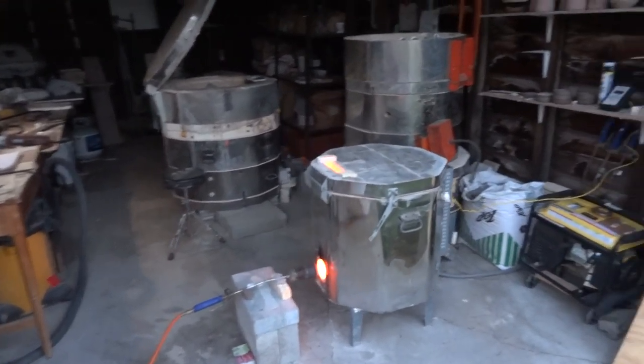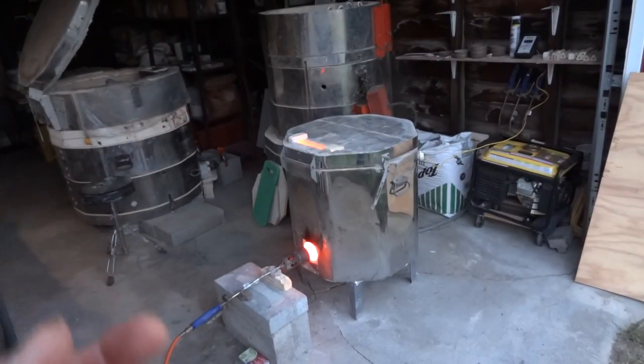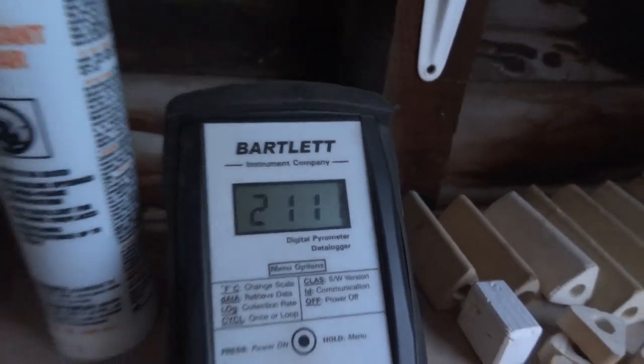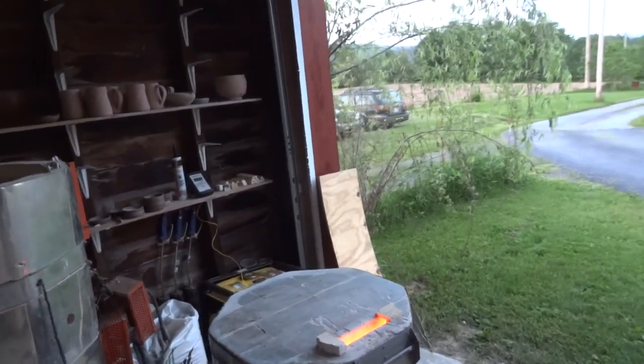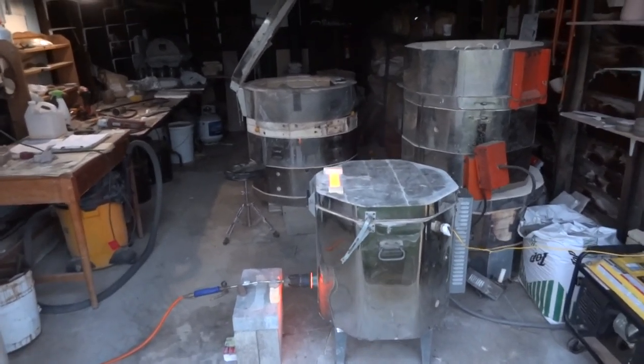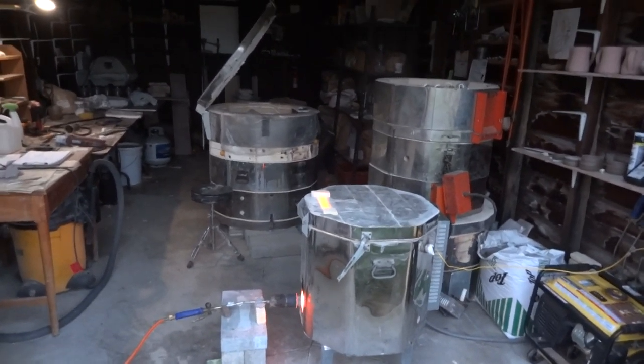I think I've hit the sweet spot now between temperature rise and getting the reduction that I want — which is what I was aiming at. It's rising quite well. That tells me I've got the flame pathways inside the kiln, the flame aerodynamics, just right — I can get reduction and temperature rise both together. That's the aim; you don't want it lopsided one way or the other.